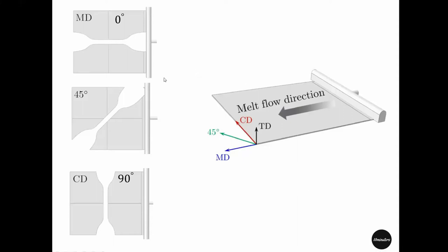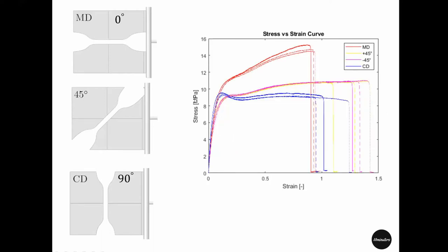Anisotropic materials have different responses in different directions. To define a Hill48 yield model, we start with three tensile tests at 0, 45, and 90 degree orientation. Force displacement response from different orientations has been converted to engineering stress strain response.